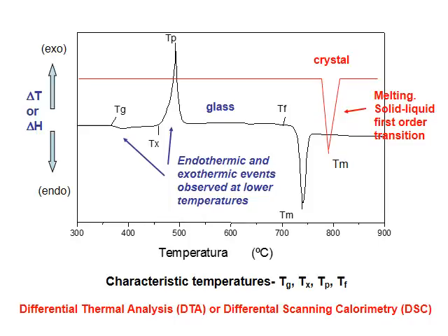In red, you have what you should obtain if you have a crystalline monophasic sample. As you heat the sample, nothing happens until it melts at Tm, the solid-liquid first-order phase transition. The black curve is what you observe for a typical glass. The initially solid and amorphous sample is heated until a certain temperature, where the sample changes from a solid to a supercooled liquid.